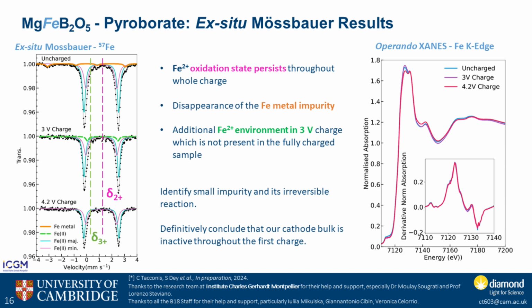We also see that the iron metal impurity, again, like we were observing in the synchrotron, disappears after the 3-volt plateau. So it's consumed during this first plateau process. And another point of note is that we see this other iron 2+ environment. It's not 3+, it's 2+ at the 3-volt charge, which then disappears at the 4-volt charge. So what was going on? We were able, through the Mossbauer, to tell that we weren't changing the iron redox, and we were able to see that we were losing this iron metal impurity.